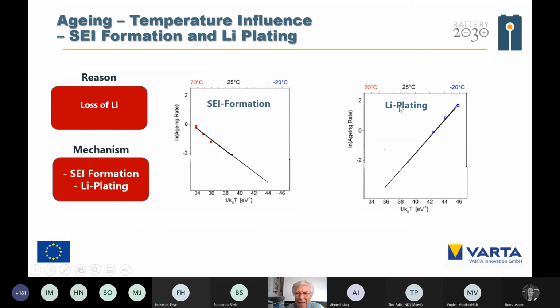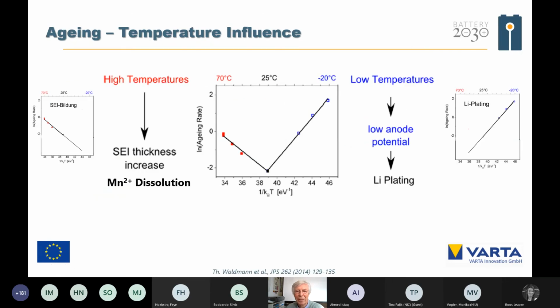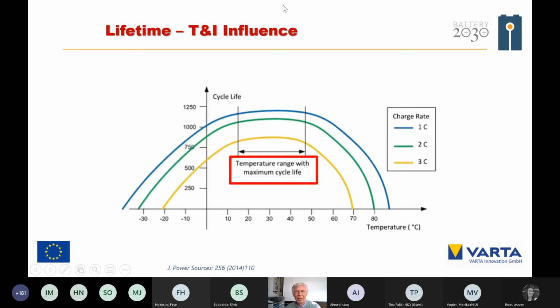But for the lithium plating, we know that at low temperature we have very high lithium plating, which goes in the other direction. So altogether, for the influence of the temperature on the aging rate, we have a minimum. That minimum is formed by the SEI thickness growth on one side, and on the other side by the lithium plating. So we have to keep in mind that we have an optimal temperature range where we have the maximum cycling life. If you go to low temperatures, the cycle life goes down, and also at higher temperatures.